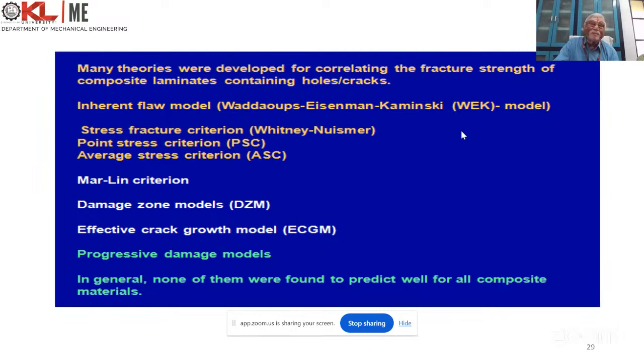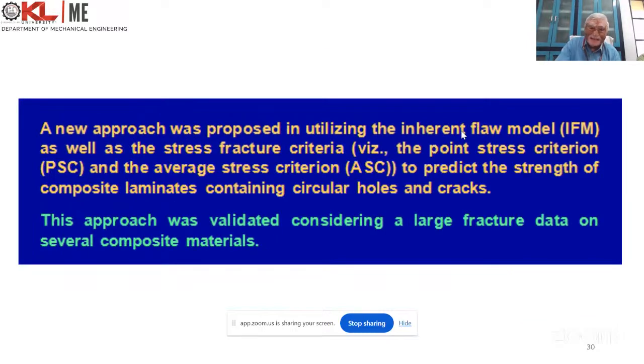So we have to select and simplify as much as possible. Otherwise it is a time-consuming process, and if some of the methods are used unnecessarily, they will alert us, but finally we will overlook that next time. We may have to pay a penalty. In general, none of the methods there are predict well for all composite materials, but we need something simple and easy to use in design. So we have developed the inherent flaw model, modified, and the average stress criterion and point stress criterion, and verified them with a large amount of fracture data on several composite materials, and finally recommended them.